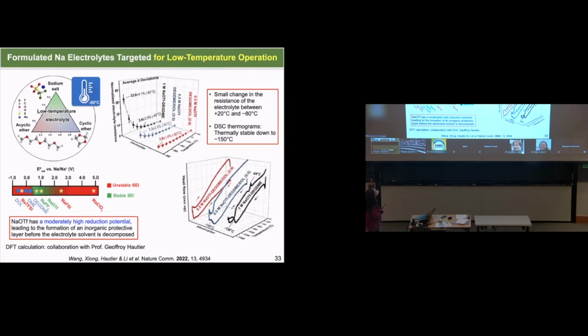We also find that for the electrolyte resistance, if you look at the blue curve and the red curve here, with decreasing temperature the internal electrolyte resistance has a very small change, even down to minus 80 degrees Celsius. So we found a very good electrolyte formulation.